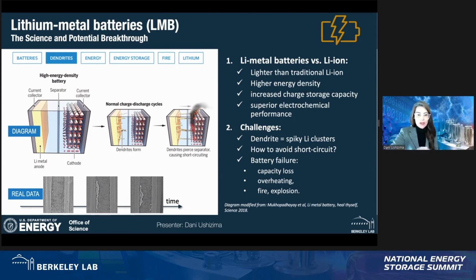Before manufacturing a new LMB design, one battery test consists in quantifying the deposition of lithium during battery charge. If the deposits form spiky clusters, we have dendrites. And if they grow, as I illustrate with our data at the bottom of this slide, that can lead to an explosion.